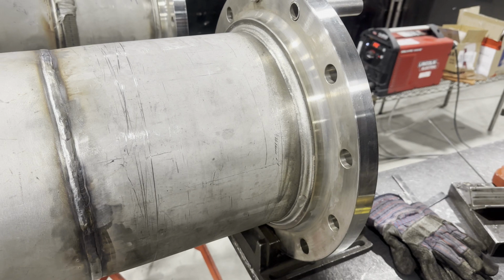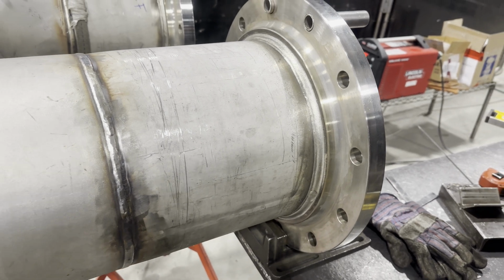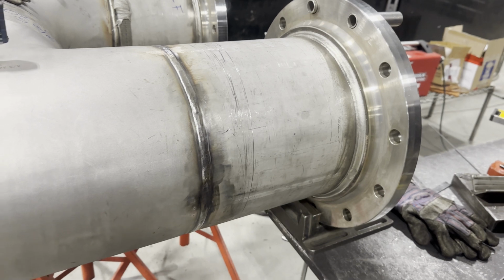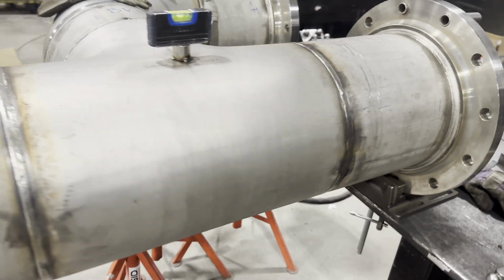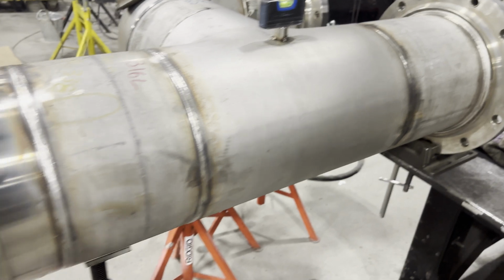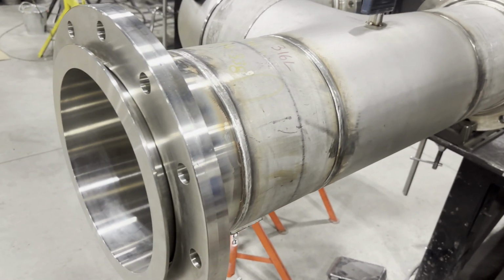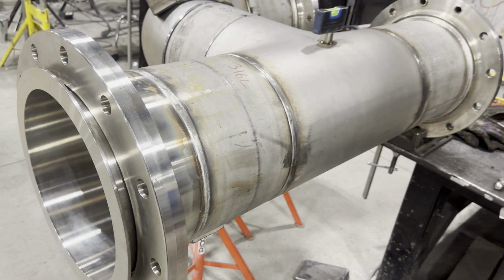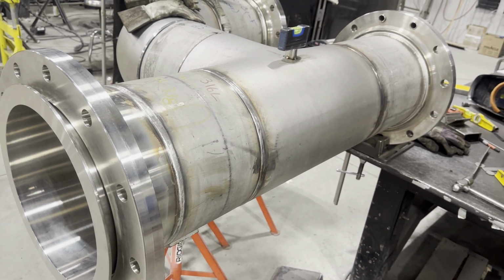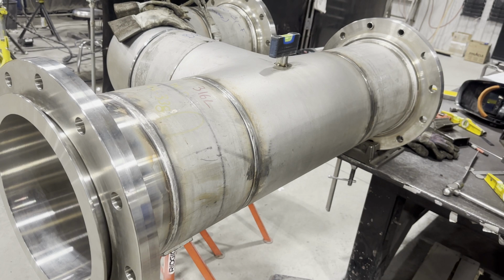It was welded by STT root and flux cored cap, so it just shrunk 1/16 per joint. If it had been welded by TIG root and TIG cap, it would have shrunk 3/32 at least per joint. It is very important to know that there is a shrinkage when welding pipes.